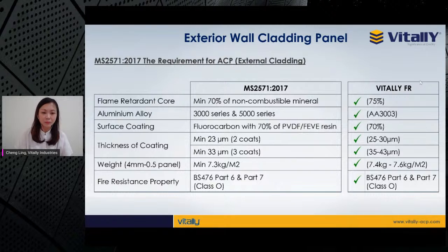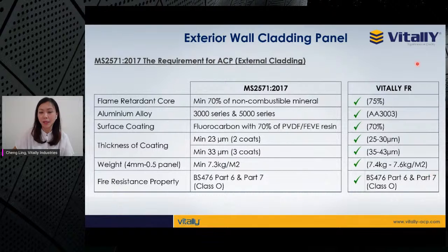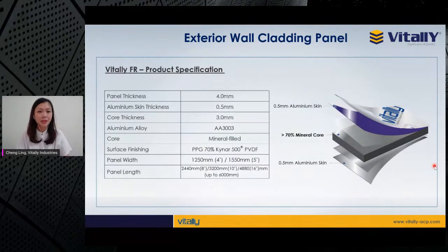The weight of the panel is also a requirement according to the standard: the minimum weight must be 7.3 kilograms per square meter. In terms of fire resistance, the panel has to meet Class O, which is the test of BS 476 Part 6 and Part 7. On the right side, you can see what we achieve in our FR panel. Basically, we meet the minimum requirements, and some actually exceed them. This is the standard spec for our FR panel.